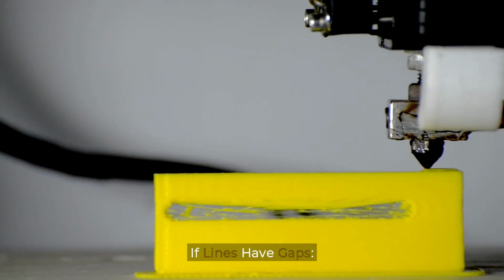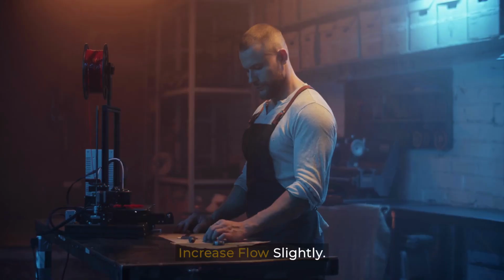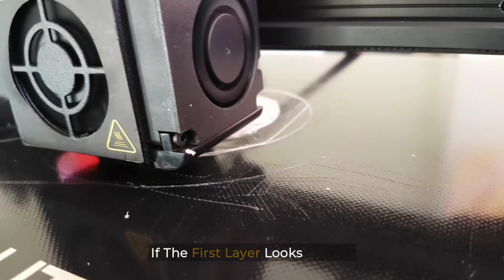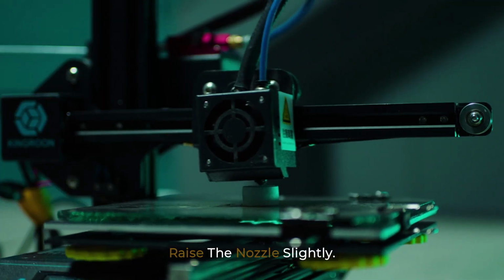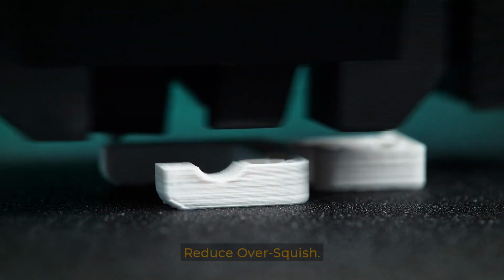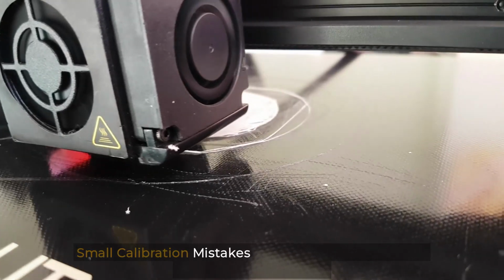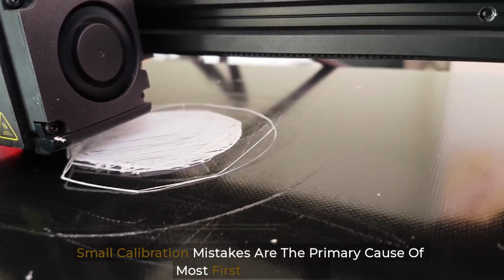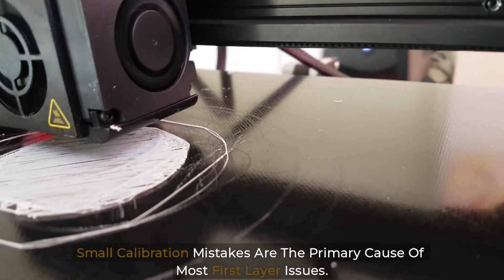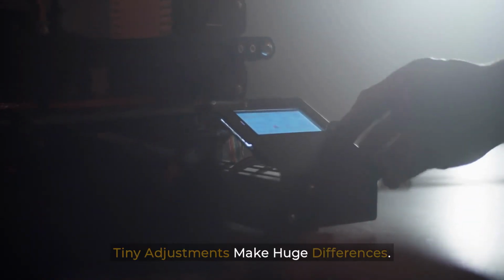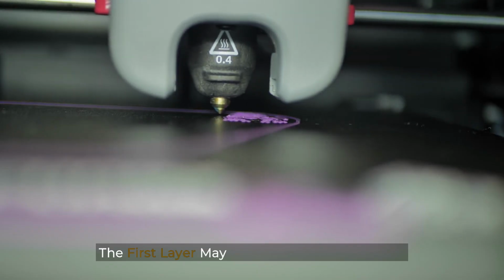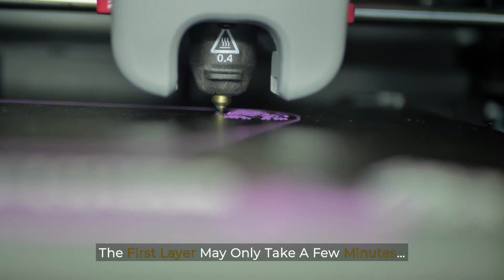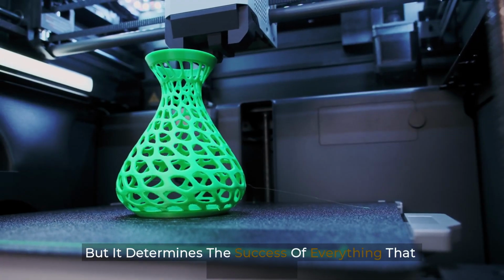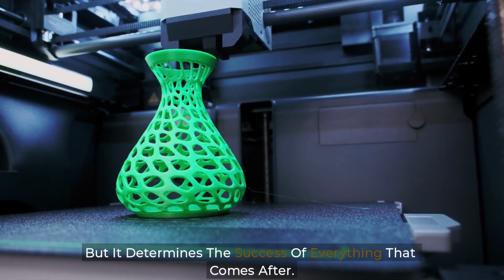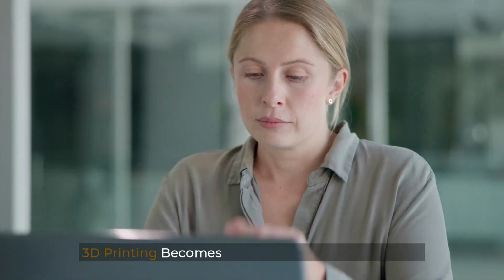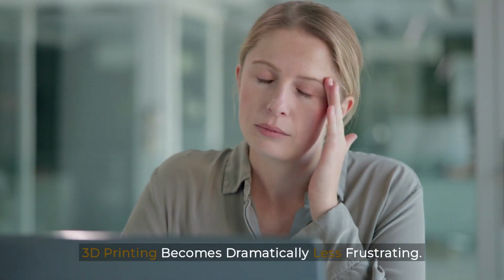If lines have gaps, lower nozzle height. Increase flow slightly. If the first layer looks rough, raise the nozzle slightly. Reduce oversquish. Small calibration mistakes are the primary cause of most first layer issues. Tiny adjustments make huge differences. The first layer may only take a few minutes, but it determines the success of everything that comes after. And once you master it, 3D printing becomes dramatically less frustrating.